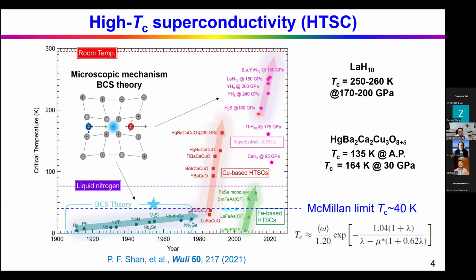Then in 2014, the superhydride superconductors were discovered, and the TC went up, but all these superhydrides can only be stabilized under very high pressure. At present, the highest TC achieved at high pressure is in LaH10, with TC about 250 to 260 Kelvin under about 2 megabar pressure, a very high pressure. At ambient pressure, the record of TC is still held by the cuprates. It is about 135 Kelvin at ambient pressure for the mercury-based cuprate, and the TC can go up to 164 Kelvin under 30 gigapascal.